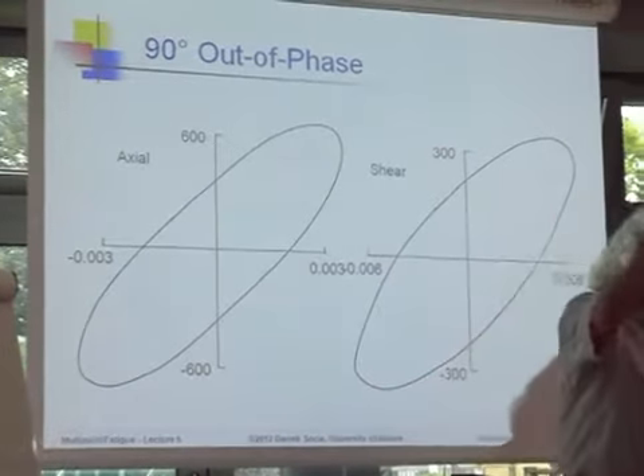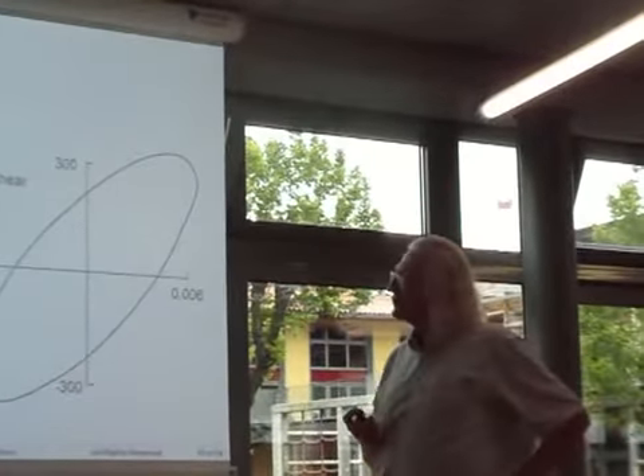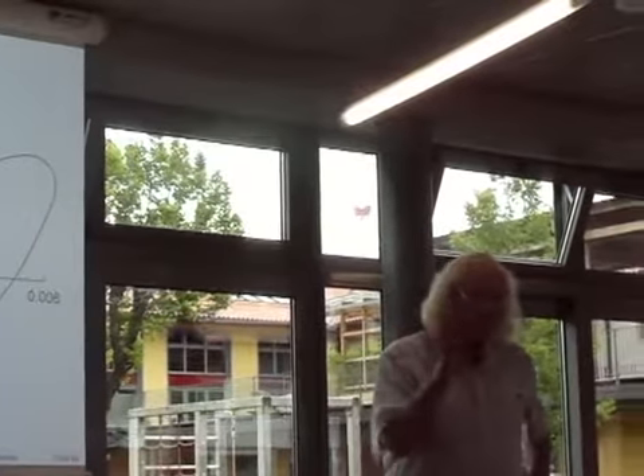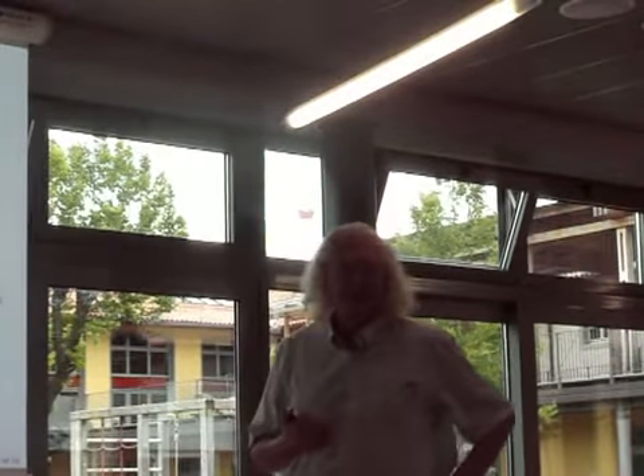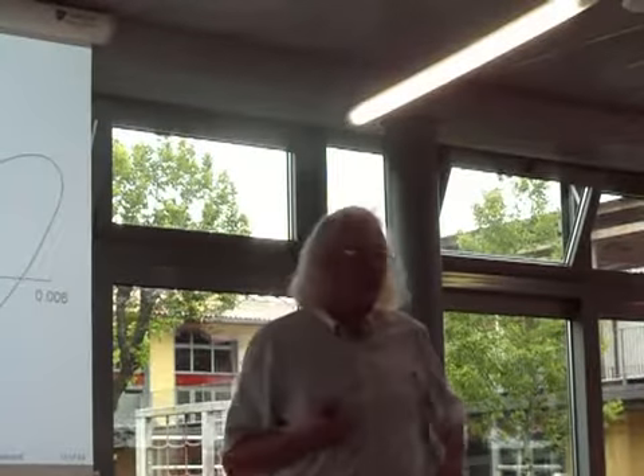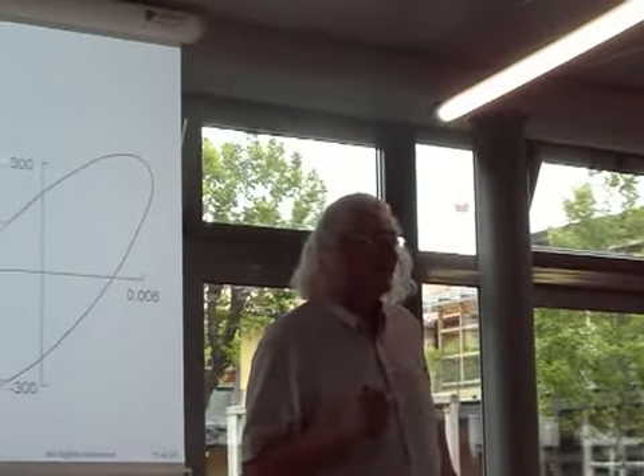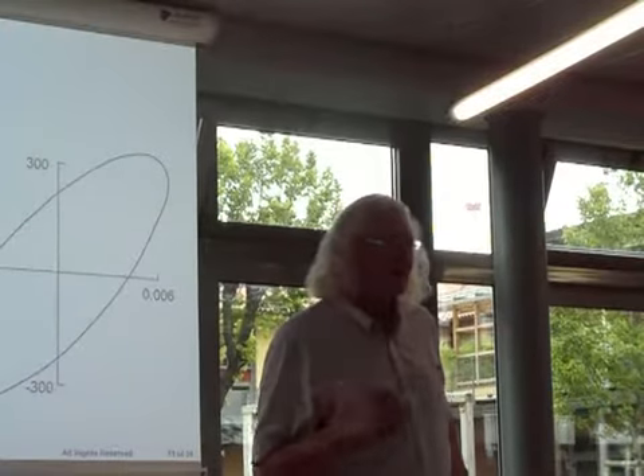That's a consequence of the coupling matrix and all the plasticity that I showed you. Look at the change in magnitude. Right? Same strain ranges. No difference. Look at the change in magnitude. Right? What would happen to the fatigue life of something if I doubled the stresses somehow? So if I double the stresses, how much will the fatigue life change? All of you can work this. 2 to what power? Right? 2 to the power of the slope of an S-N curve. Right? Easy.